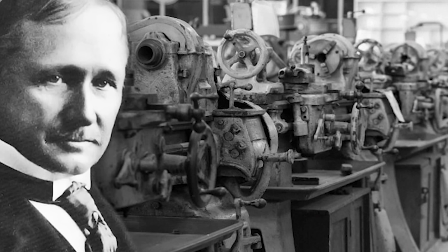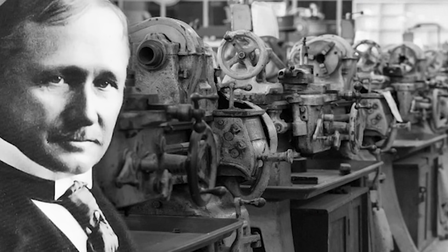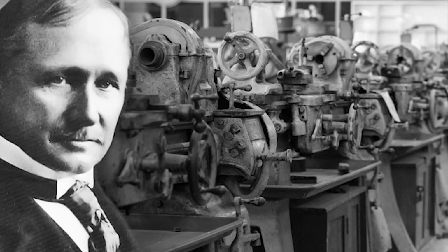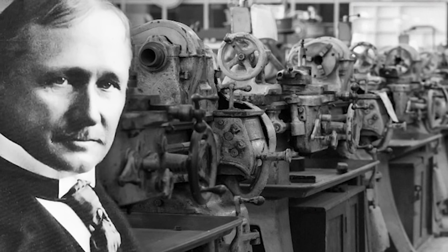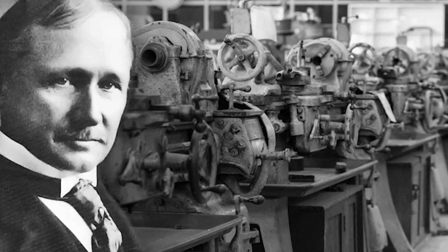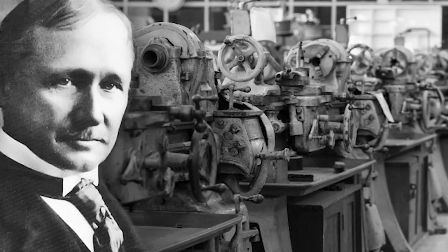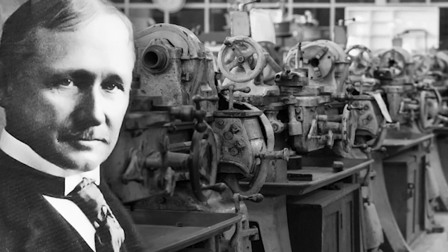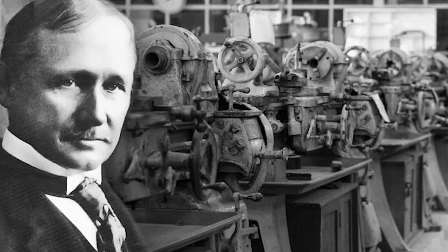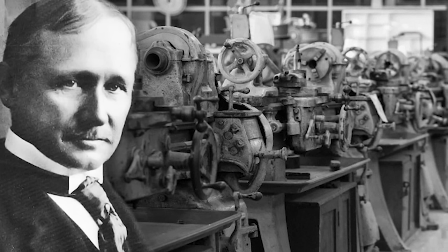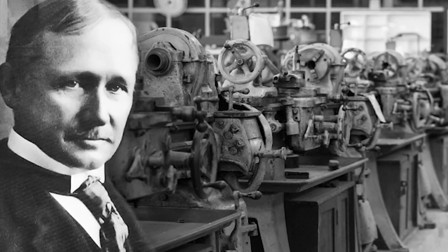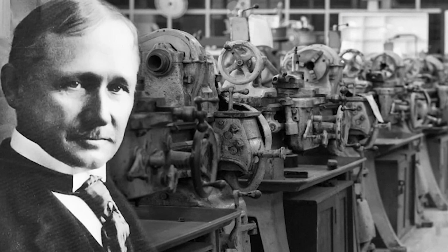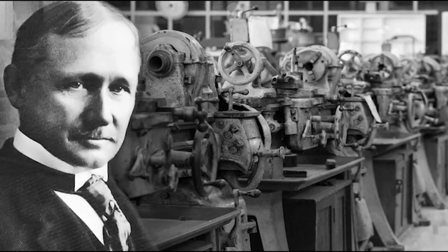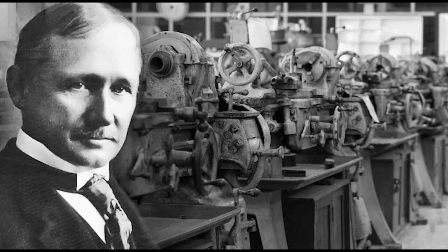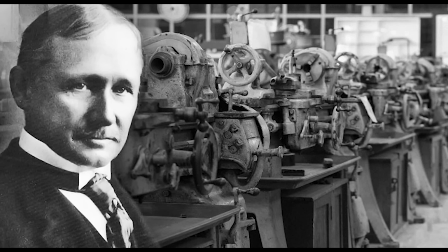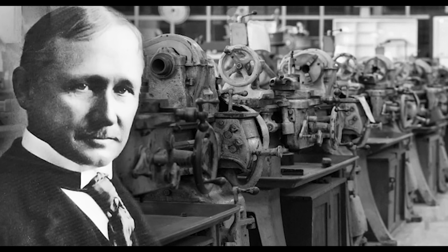European experts confidently predicted immediate failure when Taylor began the cutting operation at 90 surface feet per minute, 3 times the accepted European maximum. They had calculated that tool failure was inevitable within minutes under such extreme conditions. The mathematics of heat buildup were well established, and no steel composition could withstand the temperatures that such cutting speeds would generate. Instead, the Taylor-White tool cut continuously for 45 minutes while glowing cherry red from cutting heat.